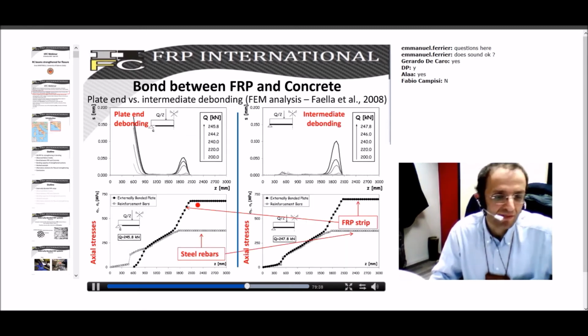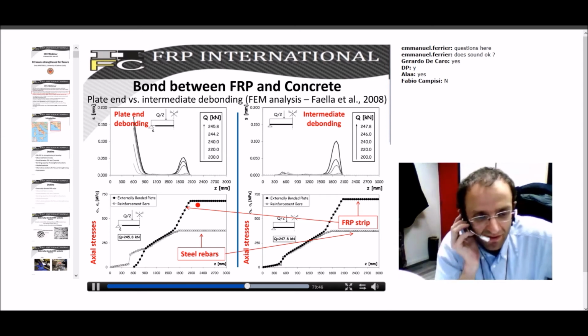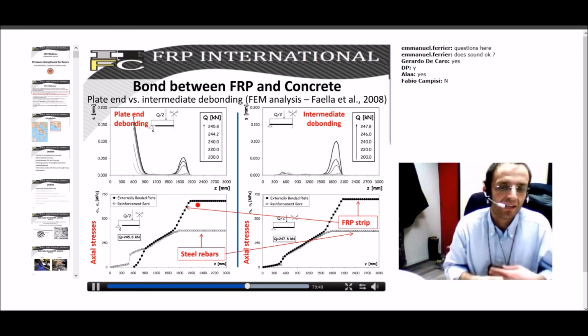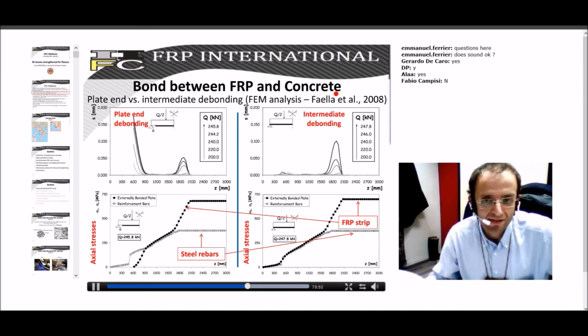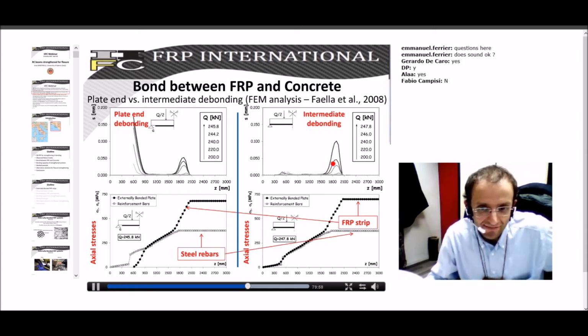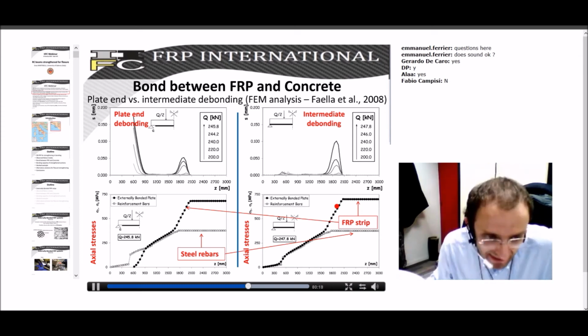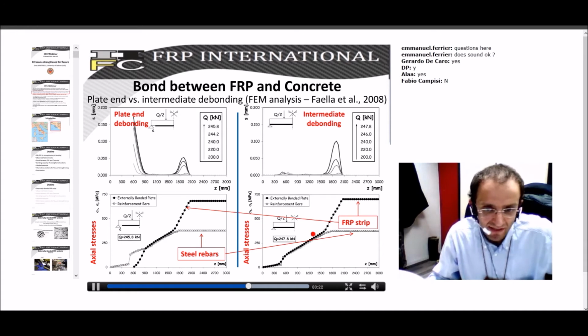You have the delta sigma in terms of strength, which will be evaluated according to the previously described models. And this is the result of some numerical analysis we presented some years ago, in which the intermediate debonding is clearly connected to the yielding phenomenon. You see, this is the distribution of stresses inside the bar. So the bar attains its yielding stress, and then it keeps constant. And from this point in which the bar is yielded, the gradient of the stresses developed in the FRP is much faster, is much bigger than below. So interface debonding occurs after yielding.